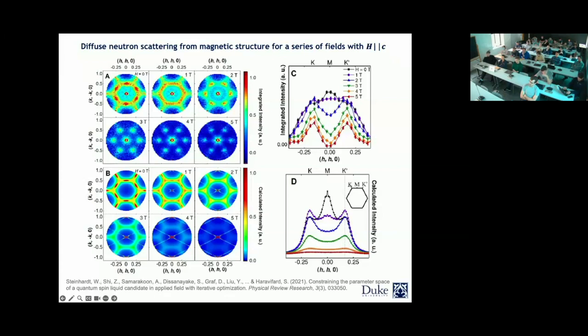However, as I mentioned, when you have the chemical disorder and everything is very diffuse, then it is going to be very difficult to look at the order parameter space, and to figure out what the order parameters are, what the values for the exchange parameters are. But what we had is a tuning parameter saying that whatever we come up with needs to follow this trend. So they were able to find a set of parameters that would basically comply with our experimental data.